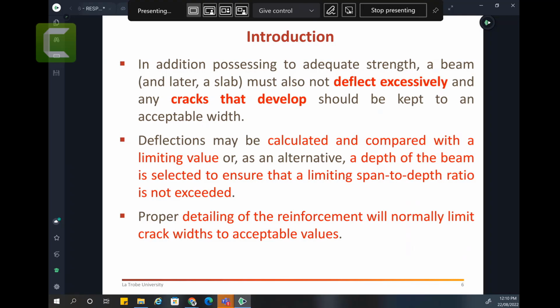However, too much deflection will again compromise the standard requirements. So engineers are required to always make sure they document what deflections they had or follow standards. Too much sagging may crack the materials, the walls which support the slab, and the finishing materials like tiles. If your slab deflected more than 20 mm for larger spans, or 25 mm in shopping centers, then the tiles and the finish will start popping up and getting cracked, which is a fault by the designer.